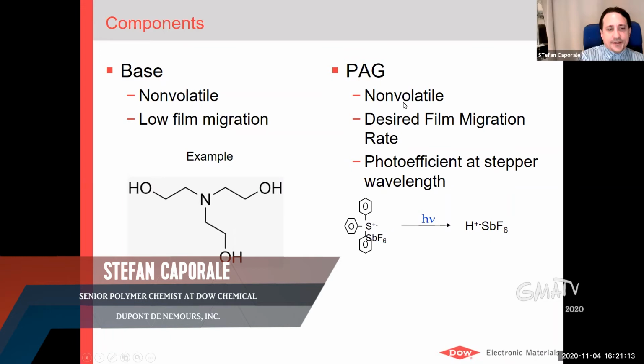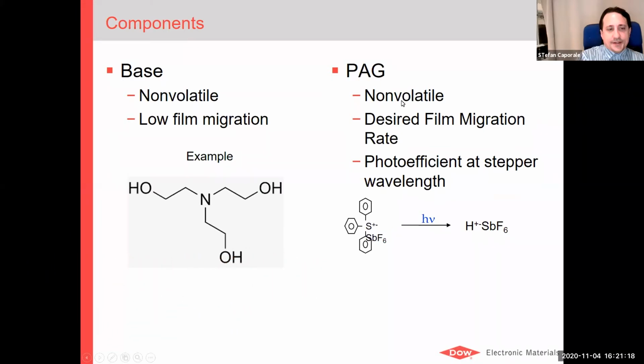Same with the PAG, we need it to be non-volatile, meaning that as you're heating it, it's not leaving the film. Also that it has good thermal stability, so in the areas where it was unexposed, it's not decomposing as we're baking the wafer to get the chemistry to happen uniformly. And then the acid that's formed has to be strong enough to do the chemistry we want, as well as photo efficient to the stepper that we're using. By that, I mean the, again, group that is absorbing all the light.